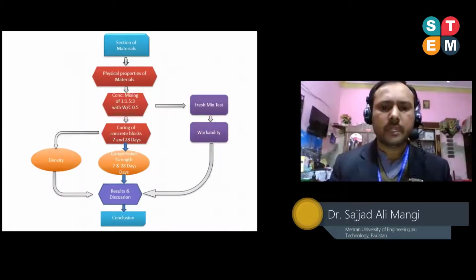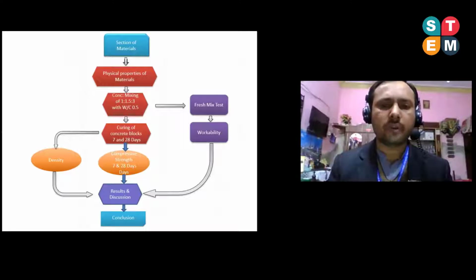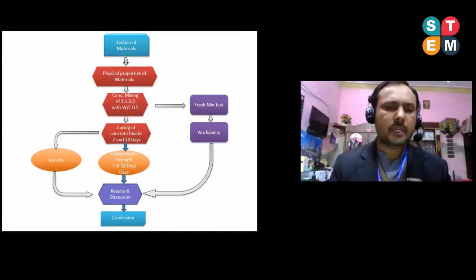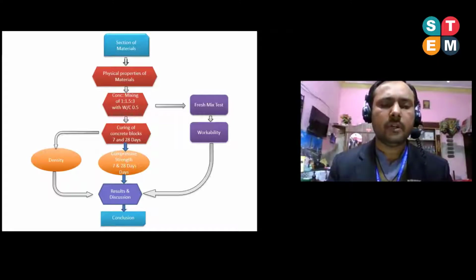So this is a flow chart: selection of material, physical properties of material, concrete mixing. A 1 : 1.5 : 3 ratio was used with a water cement ratio of 0.5. The fresh mix property was taken as workability, and then the concrete samples were cured for 7 and 28 days. And based on these, the compressive strength tests were conducted at 7 and 28 days.